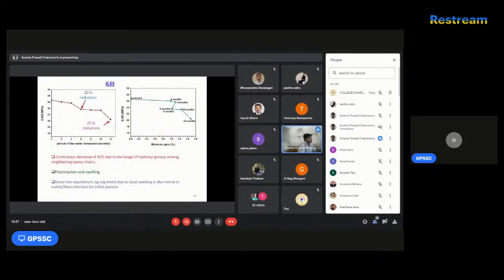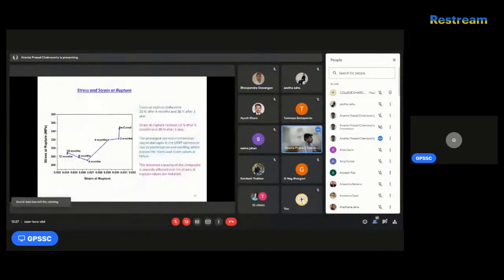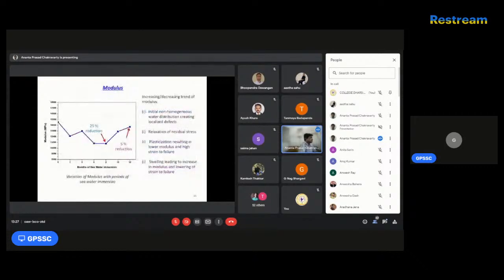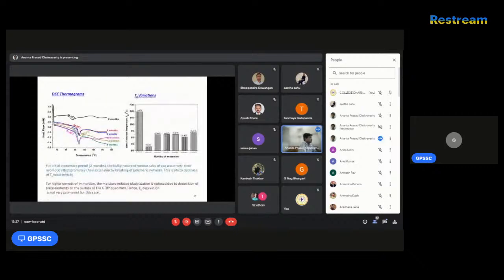After 6 months of seawater immersion, I could see a 10% reduction in interlaminar shear strength due to a non-equilibrium zigzag trend, and obviously the strength follows a zigzag trend from 0 to 12 months. It is decreasing like this, in a zigzag pattern, not directly. Similarly, after 8 months there is a 25% reduction in modulus, whereas from 8 to 12 months the modulus increases. This is very peculiar. Generally, this does not happen.